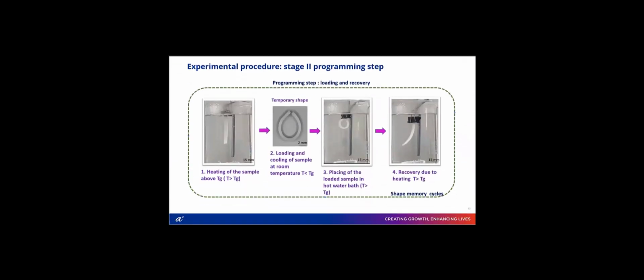The samples then undergo stage 2, the programming step of the shape memory process. Here we heat the sample, and at the higher temperature we load the sample to give a temporary shape. Again, the samples are heated, and they recover to the original shape. This single step is called a shape memory cycle, and we performed 10 shape memory cycles